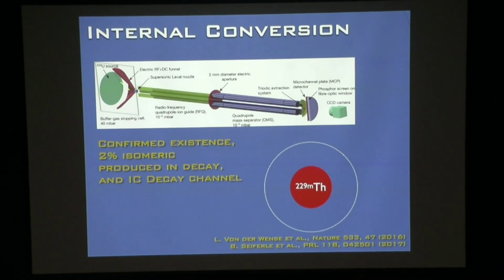Now, when you do that, you have some ion, maybe it's say thorium 3+ or something. You land it on this microchannel plate, and it neutralizes. When it does, the binding energy of this electron, the ionization potential, is actually less than the nuclear energy. So the nucleus can relax by giving its energy to this electron, and the electron shoots off. And so the MCP will actually click in that case. So you land the thorium on this, you get a click, and then 10 microseconds later, it should click again. And so they saw this, and in my mind, it confirmed the nuclear state existed.